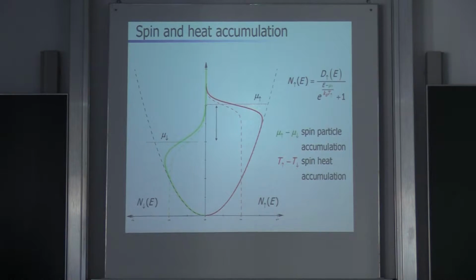Now, in this assumption, such an electron distribution looks like this: if you have a parabolic band structure, the states are filled by a Fermi-Dirac distribution function with a certain temperature, assuming thermalization. And this distribution function can change as a function of position, but very slowly. As you see in this example, the temperature of the down spins is higher than the temperature of the upspin electrons. This we call a spin-heat accumulation.